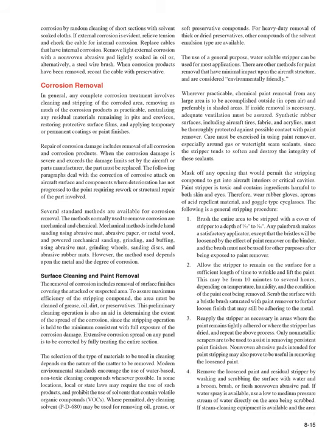2. Allow the stripper to remain on the surface for a sufficient length of time to wrinkle and lift the paint. This may be from 10 minutes to several hours, depending on temperature, humidity, and the condition of the paint coat being removed. Scrub the surface with a bristle brush saturated with paint remover to further loosen finish that may still be adhering to the metal.